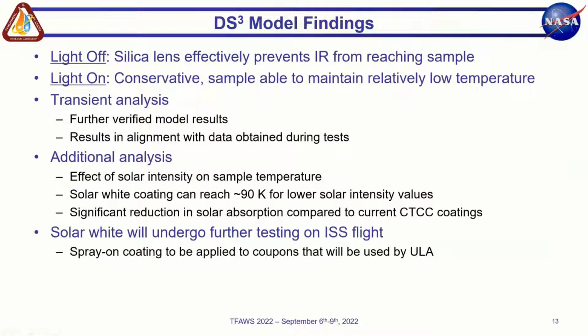So in summary, the light off case showed us that the silica lens was effective in preventing IR from reaching the sample. The light on case was a conservative one because it assumed a solar intensity of 170 milliwatts per square centimeter. So that's higher than the actual solar flux. And even with that, the sample was still able to maintain relatively low temperatures. The transient analysis further verified the results because it was in alignment with what the test results showed. And the additional analysis showed the effect of solar intensity on the sample temperature, and that the coating can reach about 90 Kelvin for lower solar intensity values.